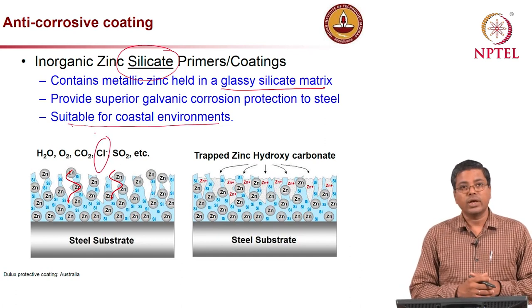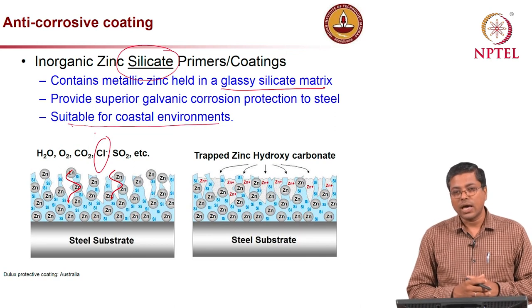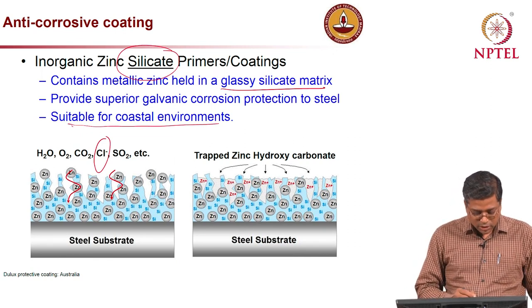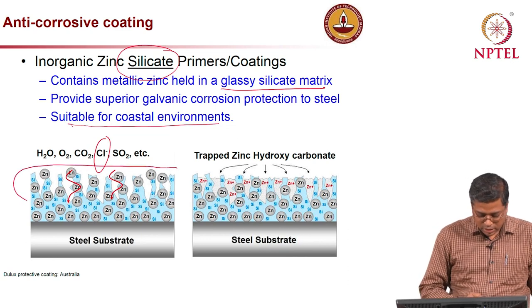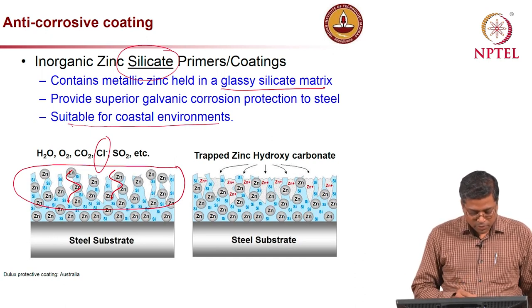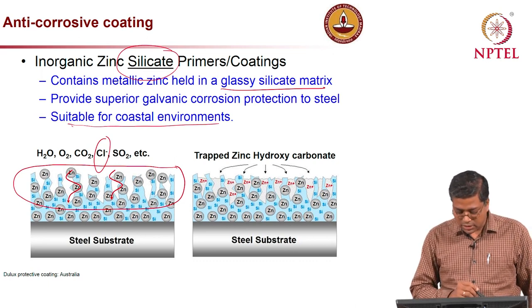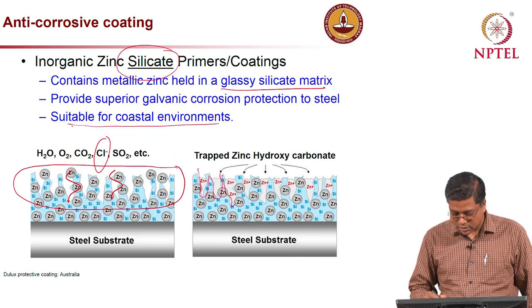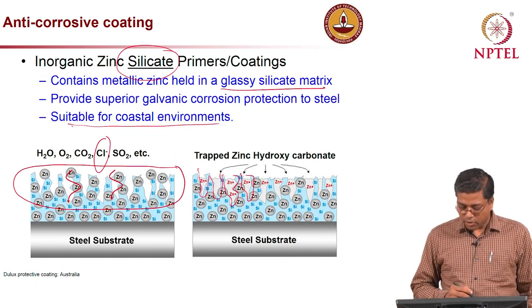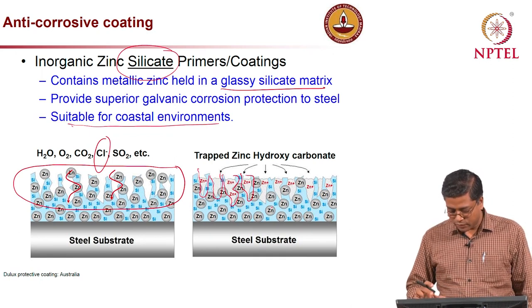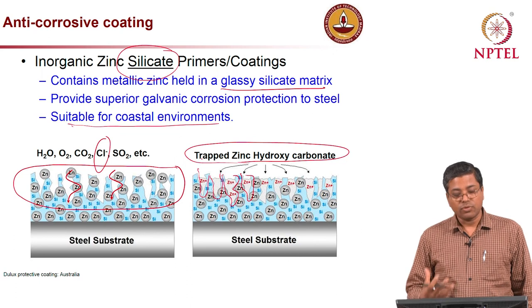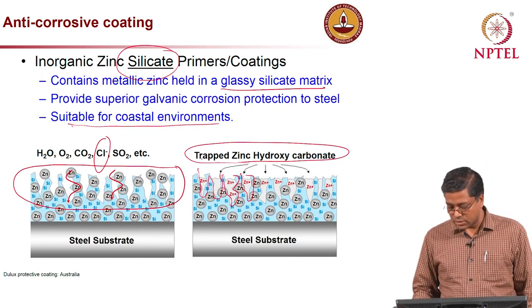In such high-chloride coastal environments, high-performing coatings are needed. Chemically, ingress of different agents from the environment creates cracks, which are filled by Zn²⁺ or oxidized zinc ions. Zinc hydroxy carbonates are formed and trapped inside the layer, providing galvanic protection.